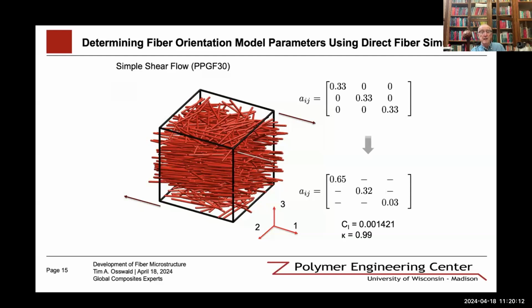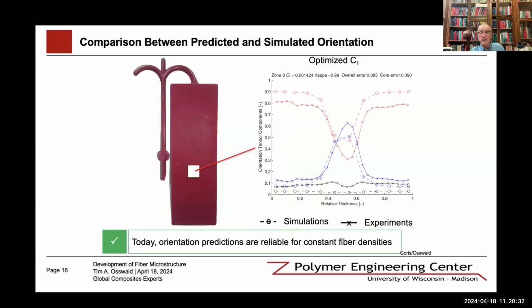For this, we then determined the fitting parameters by doing a fit in the model equation using the Folgar-Tucker model, where we have the interaction of the fibers as well as the length of it. So we can see in the simulation parameters using Moldex3D, by applying the mechanistic method to determine the fitting parameters, we can get fairly close representations of the fiber orientation as simulated and as measured.